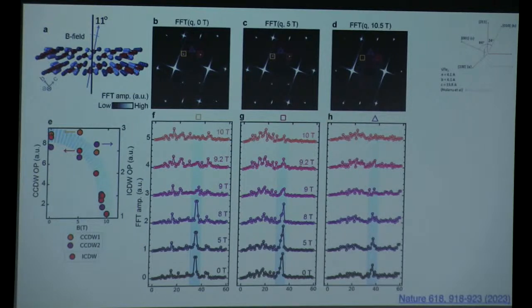So now when we apply a magnetic field, what we find is that at the HC2 of the superconductor, this charge density wave is completely gone. What I'm plotting here is the charge density wave intensity of the 3 CDW peaks, 1, 2, 3, as a function of magnetic field. You can see all of these peaks are fully suppressed by 10 Tesla. So here we have a charge density wave that disappears with magnetic field close to the HC2 of the superconductor.